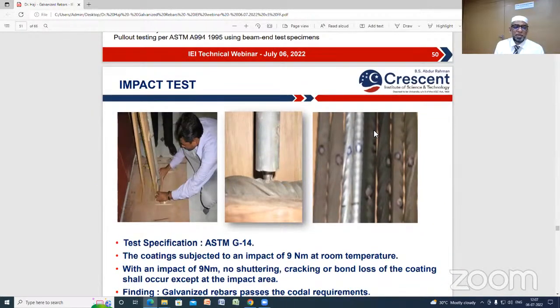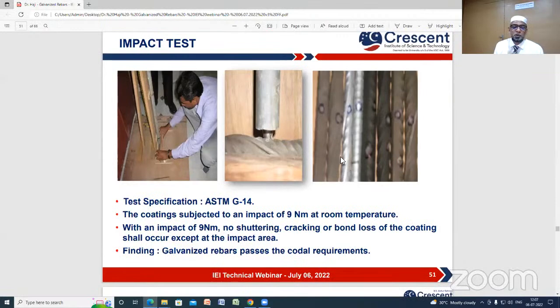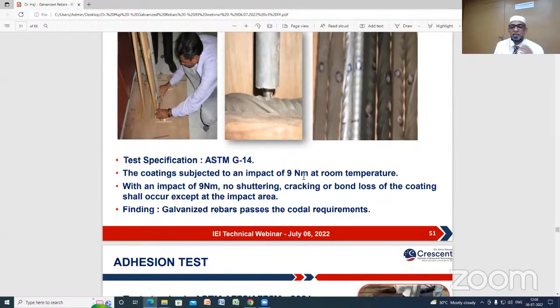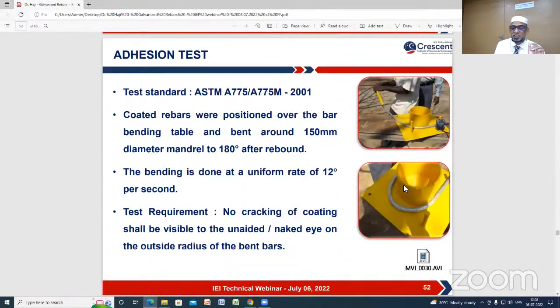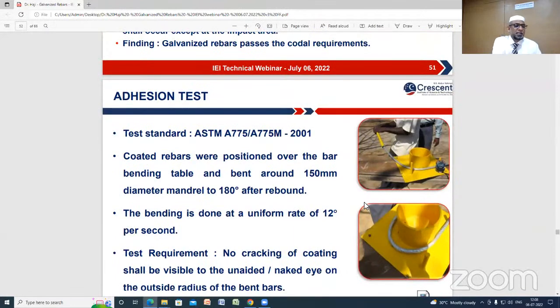Moreover, it offers excellent impact resistance when tested as per ASTM G-14. No shattering, cracking, or bond loss of the coating occurred in the galvanized rebar. It was very much intact. The adhesion test results also showed the same thing. Even after 180 degree bending, no cracking of the coating was observed. So it clearly indicates that it fulfills the requirements of the code provisions with respect to impact and adhesion tests.